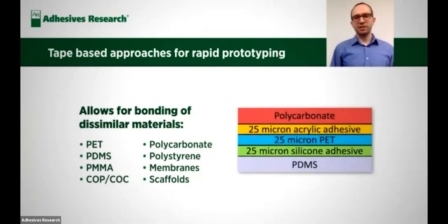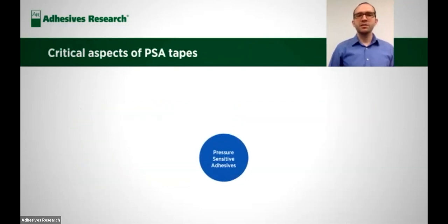For instance, I show an example here where polycarbonate can be bonded to polydimethylsiloxane or PDMS through the use of a differential adhesive tape, where an acrylic adhesive is designed for the bonding to polycarbonate, and a silicone adhesive is used for PDMS. This is something you can't accomplish using that traditional approach. However, there are some very critical aspects of a PSA tape that need to be taken into consideration when you're selecting a tape.